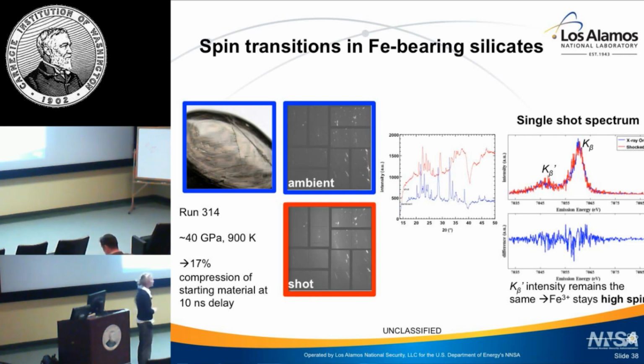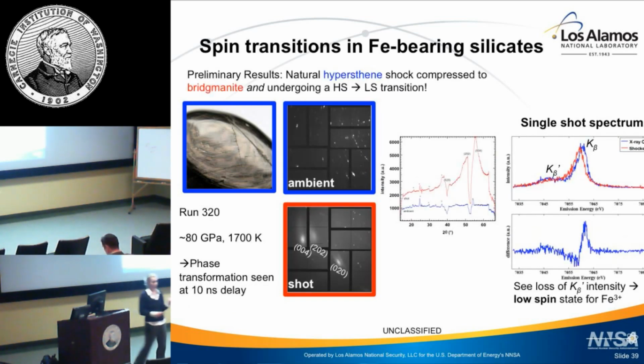Here we are at 80 GPa and 1700 K. So here's our ambient condition pattern. On shock compression, the diffraction shows some new features. Here are some lineouts of those features, and here's the area detector. These new features I can index as belonging to a bridgmanite crystalline material. So I'm saying I see a structural transition take place. This is again at a 10 nanosecond delay.